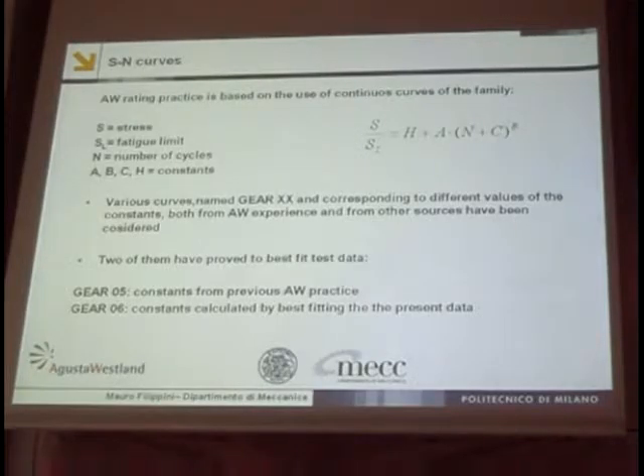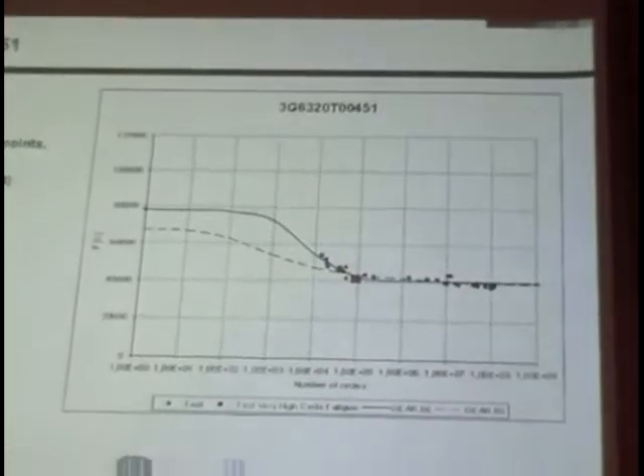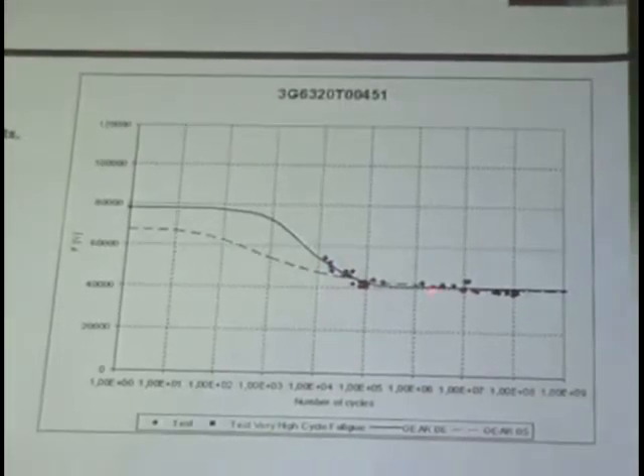But actually, AgustaWestland has a previous experience of using some shape of the curve. So we derived the fatigue data and we used the same procedure that is currently used by AgustaWestland to derive the fatigue curves. Basically they use this 4 parameters shape curve, and we have made the best fitting of data on this formula. These are the best results for the 9310 steel with the ground fillet and